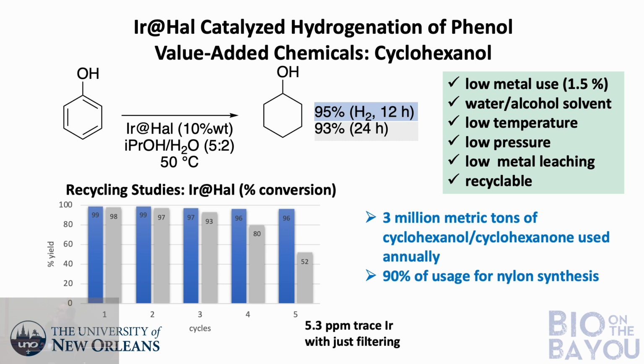Well, we've applied this catalyst to essentially the hydrogenation of phenol. Now, phenol typically is reduced industrially at high temperatures. We're talking above 150 degrees. At high pressure, we're talking hundreds of atmospheres. Okay, we can do this reaction in the lab at 50 degrees with a balloon of hydrogen. Okay, and so this reaction is done in 12 hours, 95% yield in a solvent system of isopropanol and water.